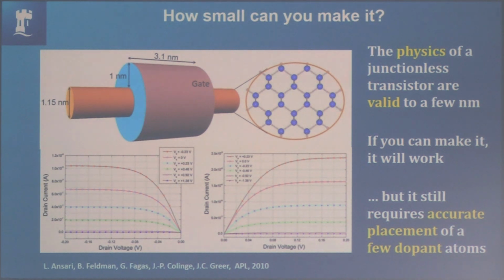Jean-Pierre came to myself and some colleagues and said, this is really interesting, how far can we scale it? So we said, okay, we'll put in a 1 nanometer device. So the cross-section of the nanowire is 1 nanometer. We put a 3 nanometer gate in it in a simulation, okay? And we put dopant atoms in there, and if you see something like this, that's a good N-type transistor. If you see something like that, it's a good P-type transistor. It seems to work from the physics. However, under the gate, we had 1 dopant atom. If you move that around, the characteristics change substantially.